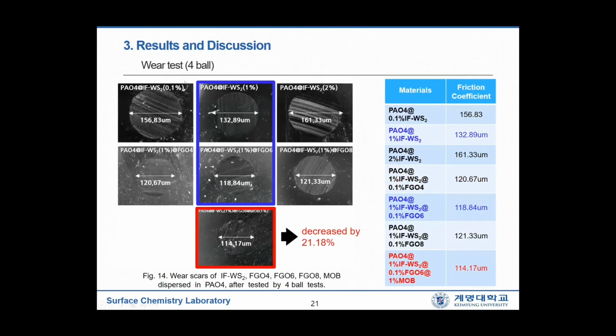This is the wear track test result for PAO and FGO samples. As you can see in this wear track pattern, compared to the wear track data tested for the PAO only, the test result for FGO samples with tungsten disulfide additive showed a decreased value in wear track. As a result, this sample, PAO4 with 1% IF-WS2, 0.1% FGO6 and 1% MOB, showed the best performance in reducing wear track by 21.18%. That's a great value.